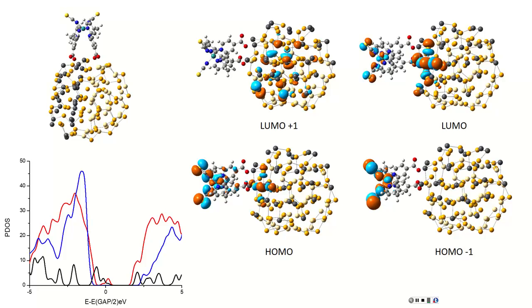So putting ligands on the leads or cadmiums will probably prevent this bending. Also putting a proton on one of the carboxylate groups will definitely not allow this, or will at least minimize this effect as well. Although we still will probably have cyanides to contribute.